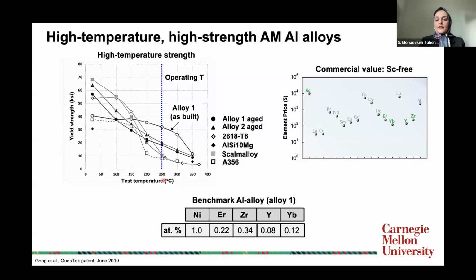For me, the target was 250 degrees C, something for a fan blade of a jet engine. At the time, the benchmark or record alloy that didn't have the highest strength but could sustain the strength much better than other options was an alloy patented in 2019 called Alloy 1, and it had five elements: nickel, erbium, zirconium, yttrium, and ytterbium in it. So the idea was, can I have an alloy that has a better performance compared to this alloy?